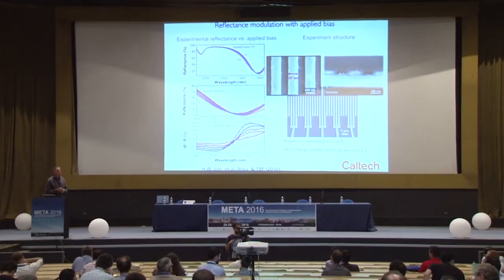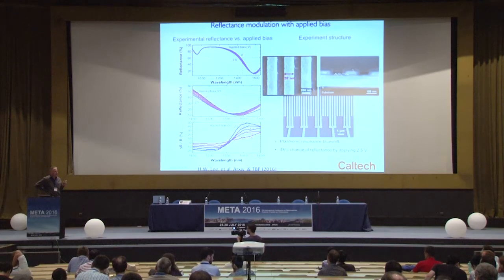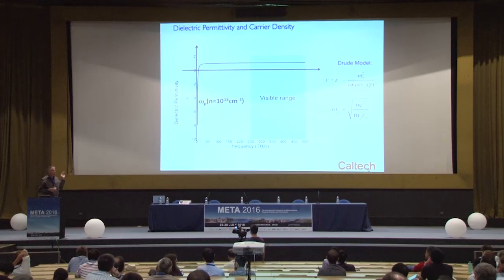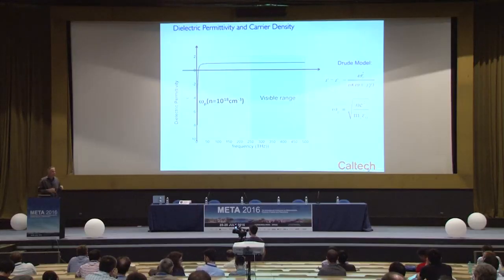Okay. So the question is, can you play the same sort of tricks with doped semiconductors? Indeed, you can. It's just that as my almost first slide indicated, the relevant frequency range for doped semiconductors will be in the far infrared. So if we were interested in doing phase modulation, we can in fact use something like a silicon MOS channel to change the complex permittivity in the far infrared. But if you want to do this at 1.5 microns for something like a LiDAR application, that was one of the things motivating our interest in the conducting oxides, to be able to do phase tuning in the near infrared. Then you have to have higher carrier density. But this is a very general picture that is applicable at a wide range of frequencies.